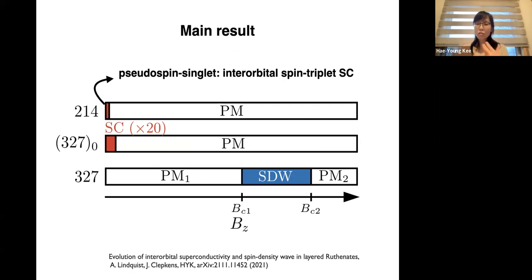In other words, at least the structure transition is not going to occur. They'll be in the same space group. You can have more rotations, but that's not a different space group. A staggered rotation angle of 6-7 degrees or 8 degrees will still be in the same phase, same structure. So there'll be no phase transition in terms of structure.